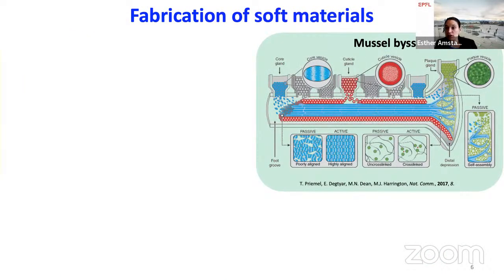If you think about how you control these parameters, it often comes back to how these materials are made, the processing. And if you look at how nature produces these kinds of high performance soft materials, you see a striking resemblance between the fabrication of these different soft materials, and that is that most of them are somehow fabricated from compartmentalized reagents, reagents that are prefabricated at very high concentrations, and then stored within well-defined compartments. And whenever nature wants to produce these materials, these compartments are released, reagents are locally released, and that allows nature to control local composition and to locally non-linearly vary it, and to a certain extent also to control the structure over very different length scales.